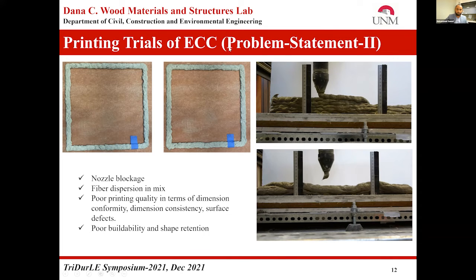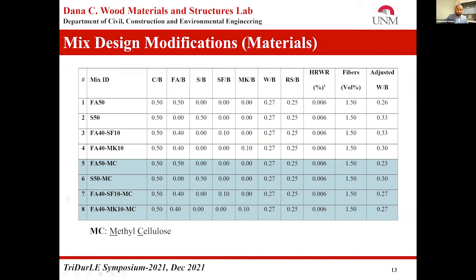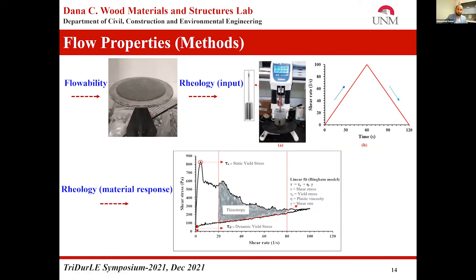To address this challenge and fix the printing quality, we used a viscosity modifying admixture, that is methyl cellulose, which yielded 4 more ECC mixes. The experimental program was designed because the fresh properties, especially the rheology, are of very high importance to get a printable 3D printed concrete.